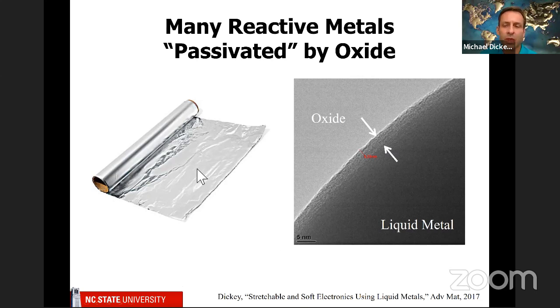And so this is a picture of aluminum foil, which you probably have in your kitchen. And you'll notice that aluminum foil never has rust on it. And that's because the oxide forms a barrier so that the aluminum underneath it doesn't react with the air that surrounds it. It's like a protective layer. And so we've looked at little droplets of liquid metal through a transmission electron microscope. And we found that you can see the oxide layer. It's a few nanometers thick. And it forms, and kind of to a first approximation, it doesn't really get thicker. So think of it as about a 3 nanometer thick layer.